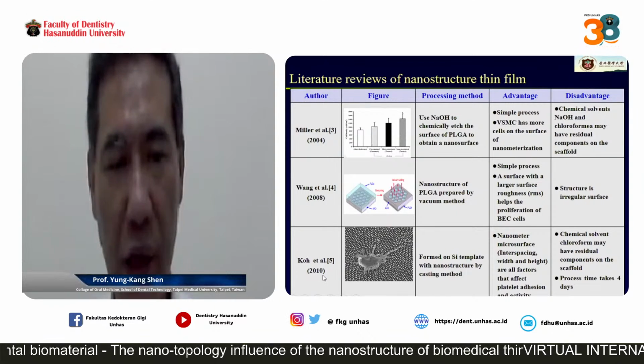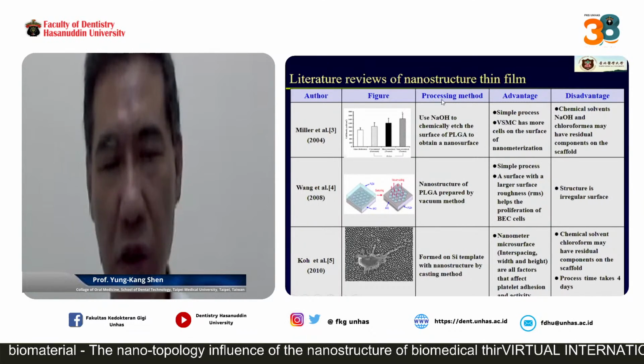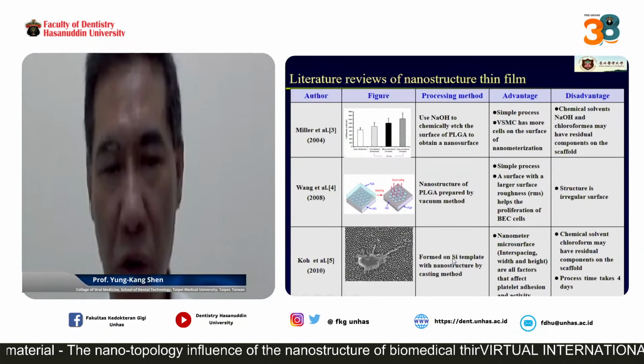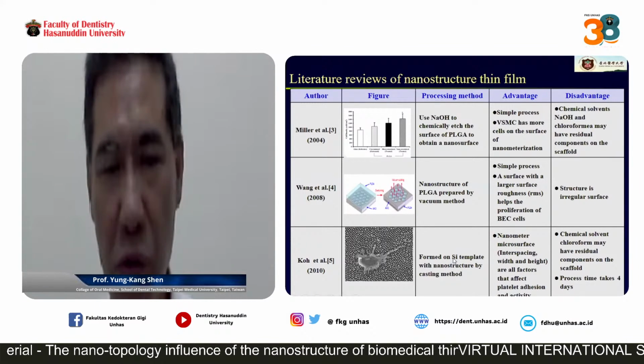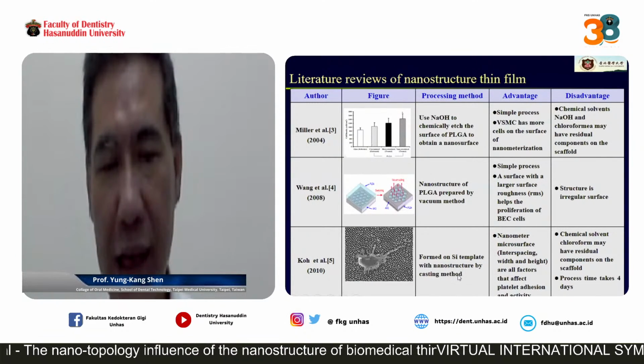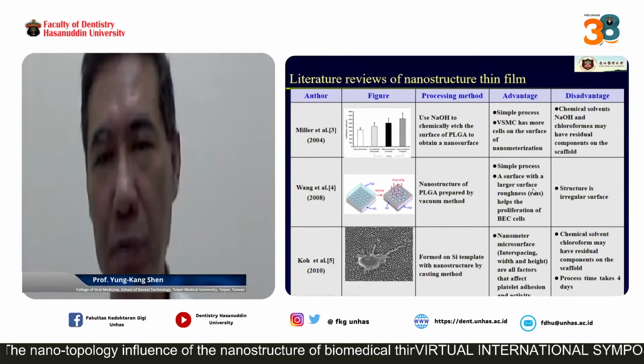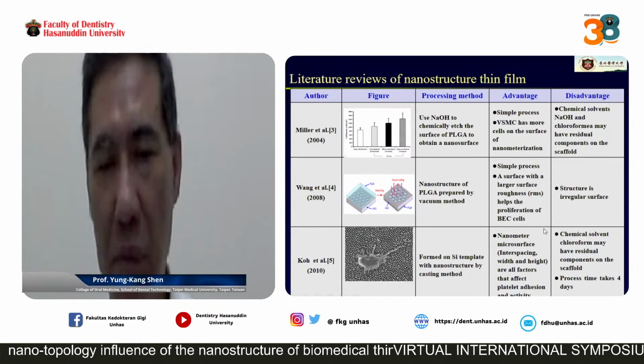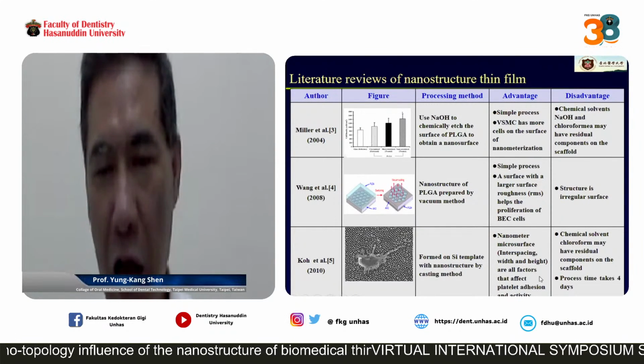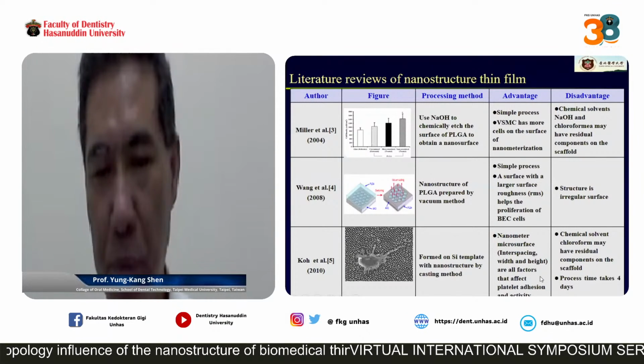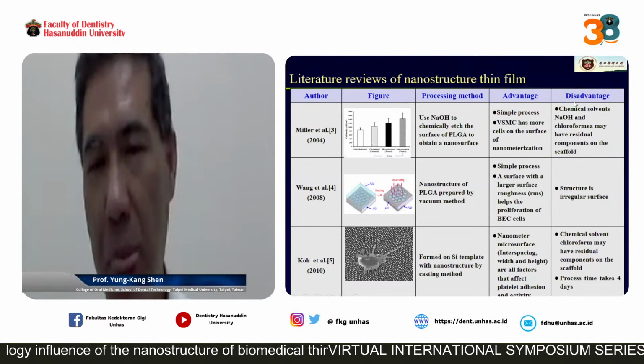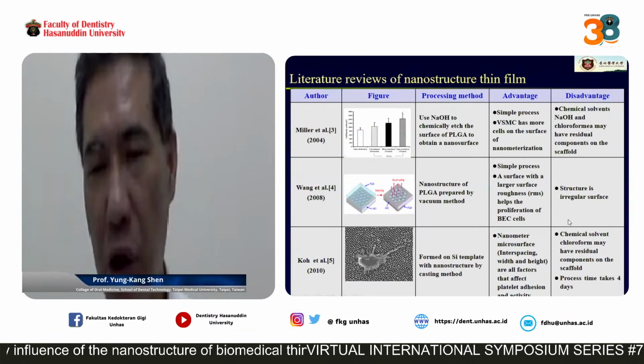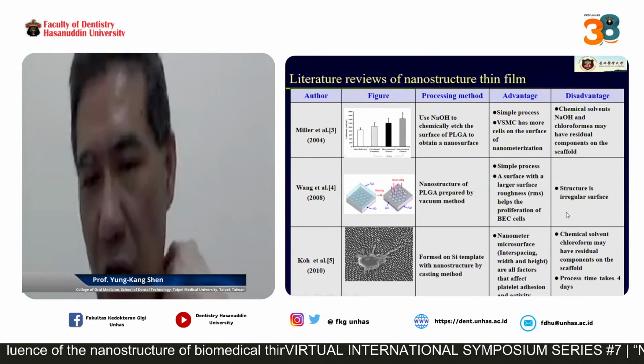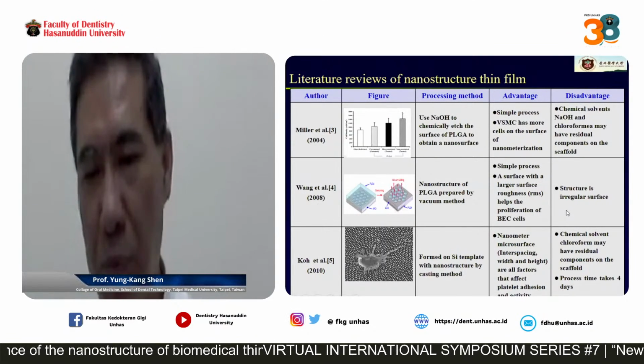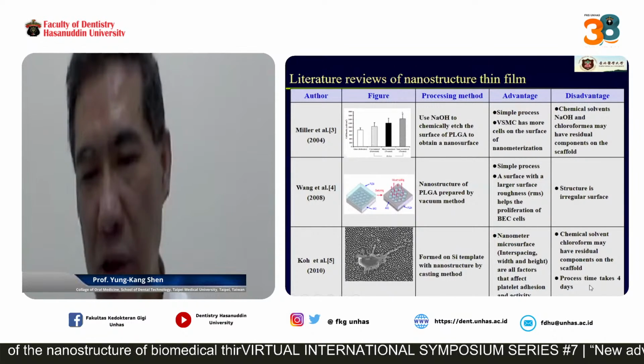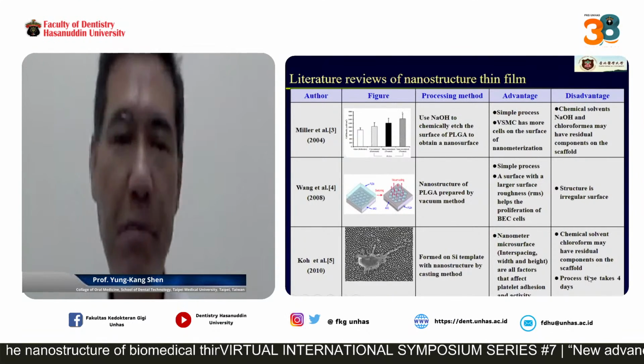Koh et al. in 2010, their processing method uses formed on Si template with the nanostructure made by the casting method. Their method's advantage is that nanometer and micro structures are all factors that affect platelet adhesion and activity. Their method's drawback is that the chemical solvent, such as chloroform, may leave residue components on the scaffold, and their processing time takes 4 days, which is too long.